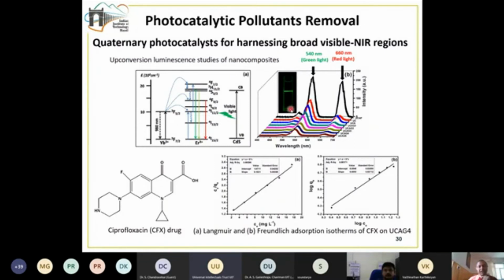And thus we can clearly see even from a visible light naked eye experiment, wherein you take this upconversion nanoparticle, disperse it in a solvent like water, and then you have an NIR laser. Just like this is a red laser, you have an NIR laser, which we cannot see. You just pass it, and wherever it passes through the sample, you can see a bright green line, which is shown here. It's in a cuvette, and the bright green light shows the upconversion property. Then, after doing all this characterization, we utilized it for the photocatalytic pollutant removal experiment, wherein we chose a colorless pharmaceutical pollutant, which is the ciprofloxacin drug.